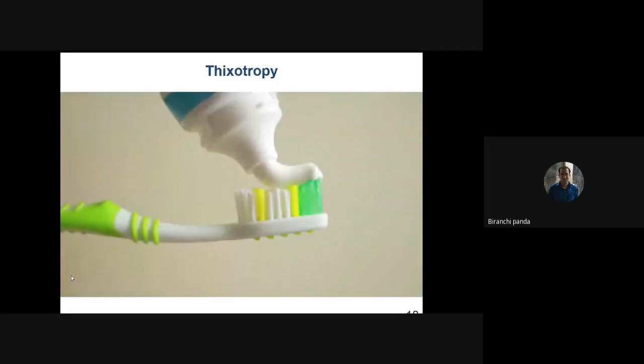If you simply extrude it on the brush, it remains in its original position. It never deforms. But you apply a very small pressure to extrude this paste out of the tube. So once you apply pressure, it can easily extrude out from the tube. But once you release the pressure, it remains in its own shape and position. So this is something called thixotropy. It means once you apply some high shear rate, the material will lose its viscosity. So when you are squeezing the tube, the material is subjected to a high shear rate, and this paste can easily come out of the tube. But as soon as you release your force, the material can recover its viscosity and remain in its own position.